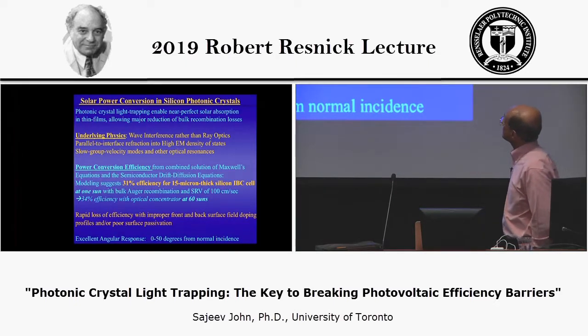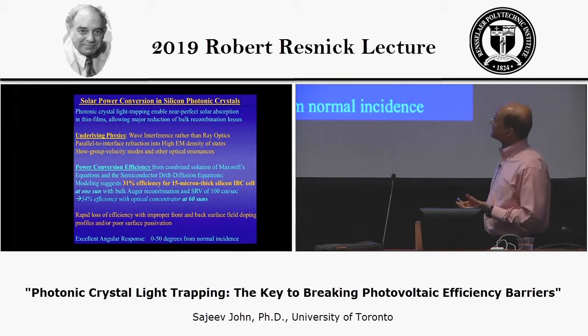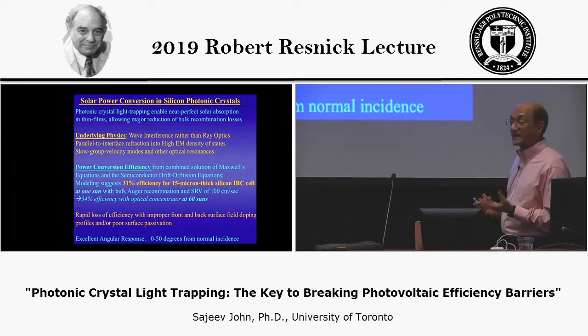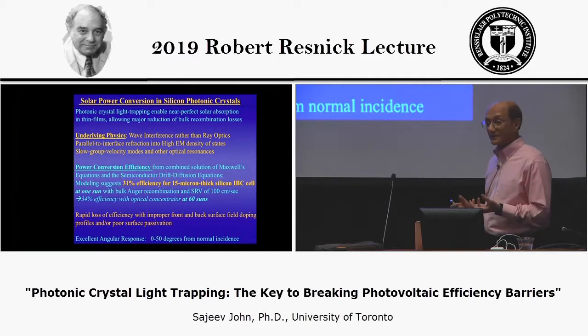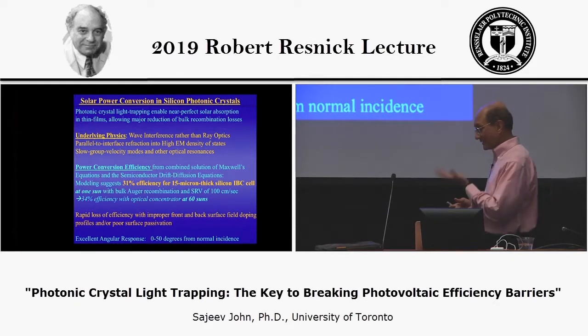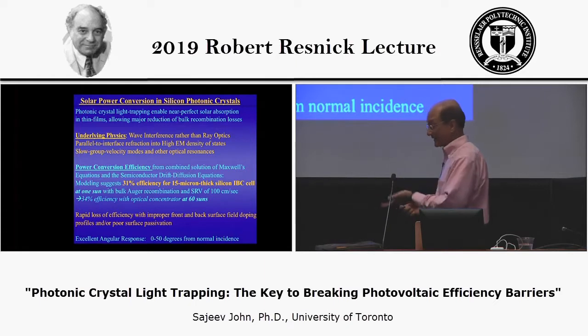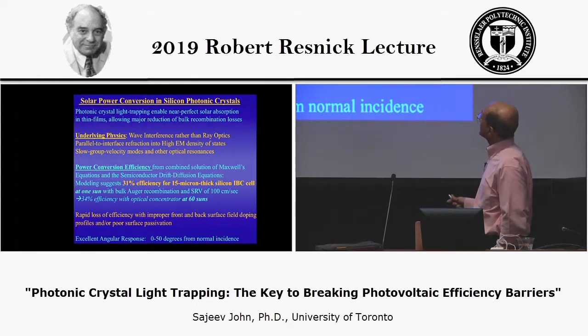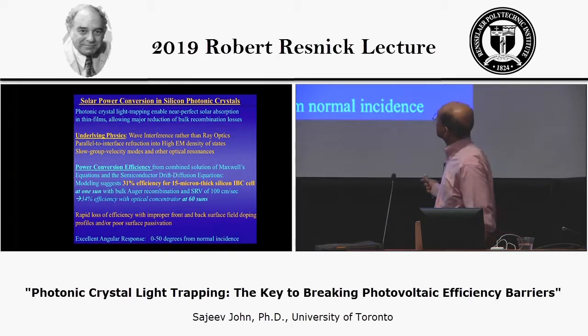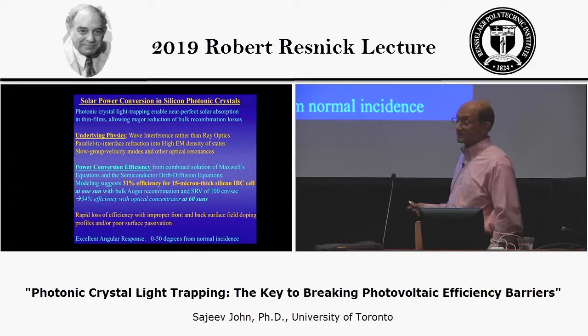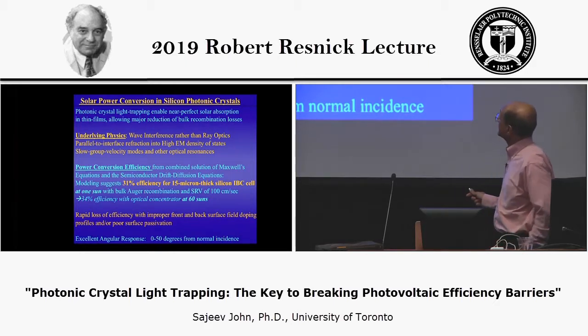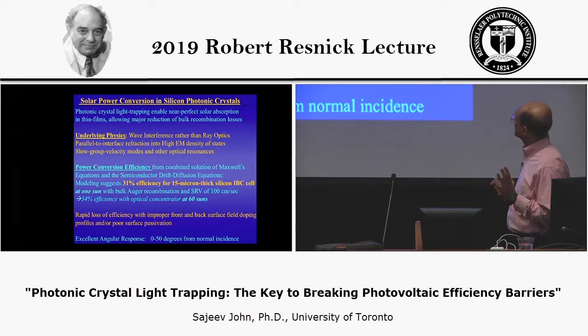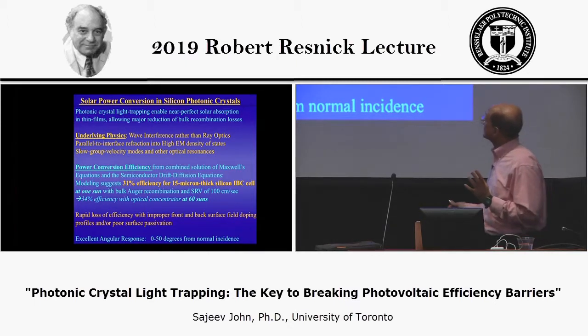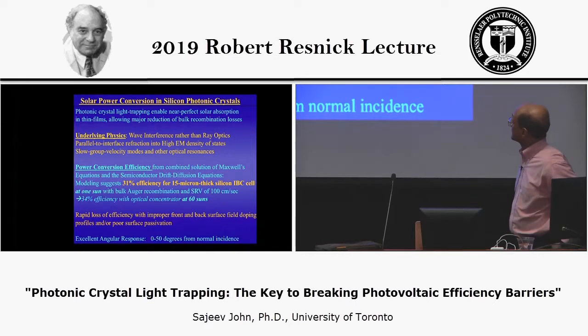So in summary, let me just say that photonic crystal light trapping should enable very high solar absorption in thin films, allowing a major reduction in bulk recombination losses, which is the major barrier between the current world record and the Shockley-Queisser limit. The underlying physics is wave interference rather than ray optics, leading to these parallel to interface refraction effects, the high electromagnetic density of states that supports these slow group velocity modes, and other optical resonances.